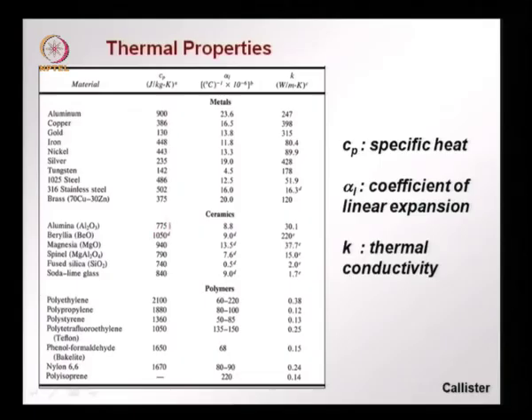Ceramics are slightly in the higher end of the same range, going from about 700 to 1050 joules per kilogram Kelvin. Polymers much higher, almost double the values that we see in the ceramics and aluminum or more. So, more heat is absorbed for a unit change in temperature. Coefficient of thermal expansion, again we see a wide range, with metals having values in the range of 5 to about 25 times 10 to the power of -6 per degree Celsius. Ceramics ranging from 0.5 to about 15, and polymers having much higher values, more expansion in most of the polymers.